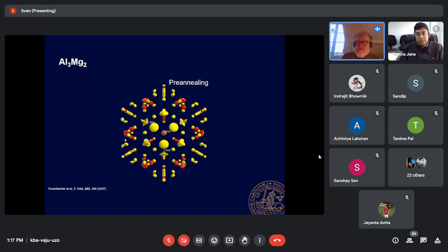But if you anneal the crystal, this changes, and you get a very nice image of almost perfect spherical atoms, which is telling you that this is certainly the right solution. Looking again at the pre-annealed sample, some atoms are really misbehaving, but after annealing, everything looks fine.